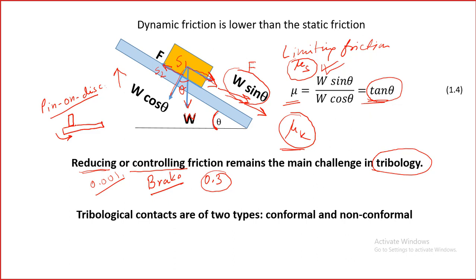As the disc rotates, the pin will experience some force because of friction. With proper orientation you can put a load cell here to stop this movement, and the force measured by the load cell will equal the friction force. You can apply load using a dead weight or some mechanism. As the disc rotates you can continuously measure friction force over time.